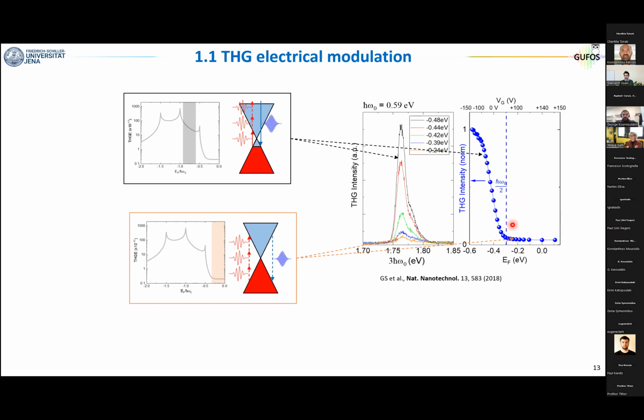Now, I want to point out, if you look at this graph, it is the first demonstration of gate-tunable nonlinear optics in graphene, so gate-tunable third harmonic generation. Note that we only go from 0 to negative values of the Fermi energy. And this is a limitation of the samples that we were using and the fundamental photon energy that we were using. So we only see enhancement in one direction, and we cannot probe this part here. This will be important in a few slides from now.